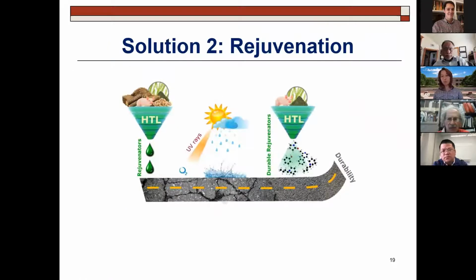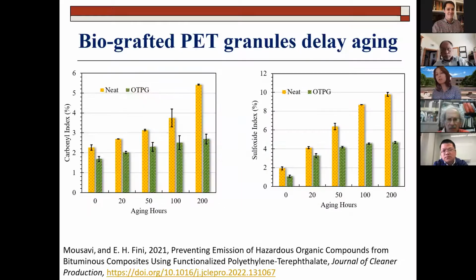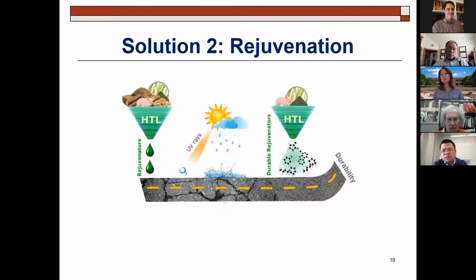Solution number 2 is for when the aging has happened to some extent. And I showed you here, even with the green, the aging happens, right? The green is still going up. It doesn't go as high as yellow, but it's still going up. So some level of aging happens, even with our best case scenario, the best case solution of number 1. So maybe we should combine solution number 1 with solution number 2 to have a synergy. And solution number 2 is to continuously add rejuvenator and make sure your asphalt stays as good.